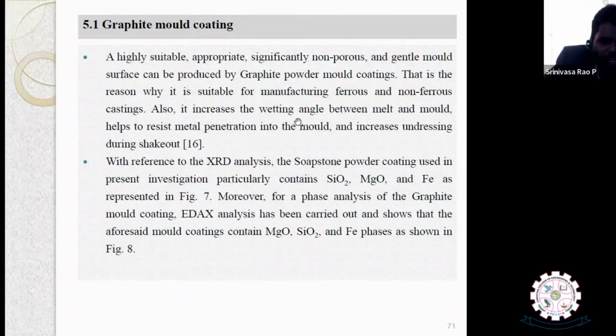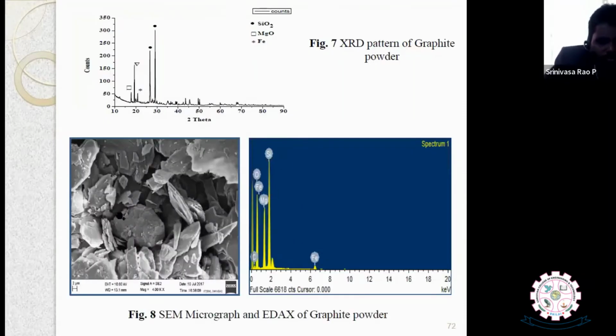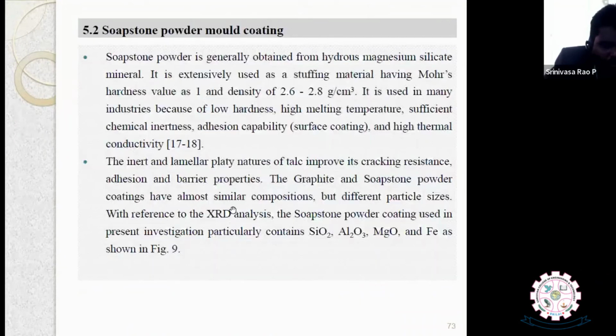It increases the wetting angle between the melt and mold, and resists the metal penetration into the mold. So this is the XRD analysis and SEM analysis that we have carried out on the graphite. And why we use soapstone powder: it is obtained from the hydrous magnesium silicate mineral. It is extensively used as a stuffing material, having a hardness value of 1 and density of 2.6 to 2.8. It is used in many applications because of low hardness, high melting temperature, sufficient chemical inertness and adhesion capability, that means surface coating, and high thermal conductivity.